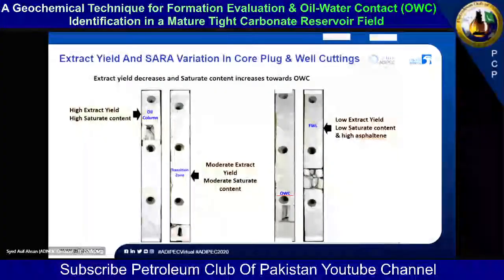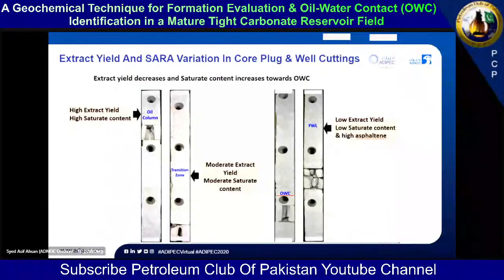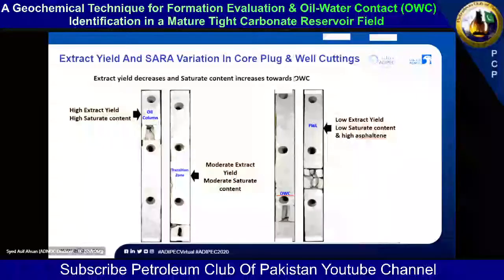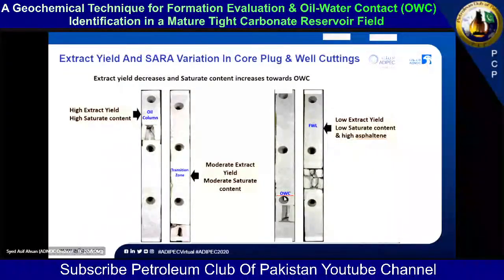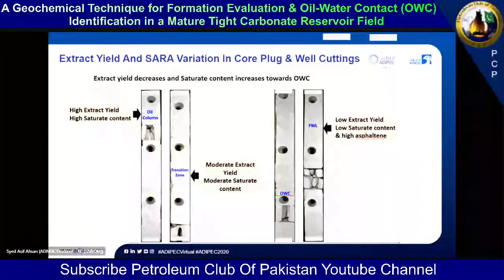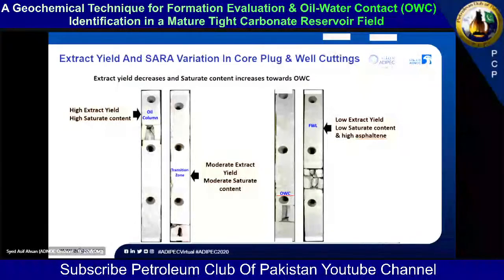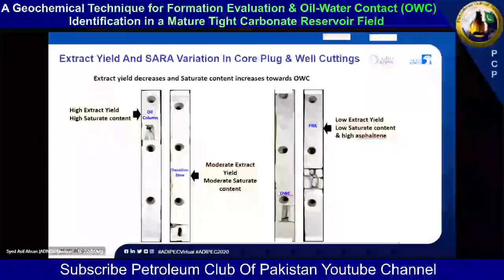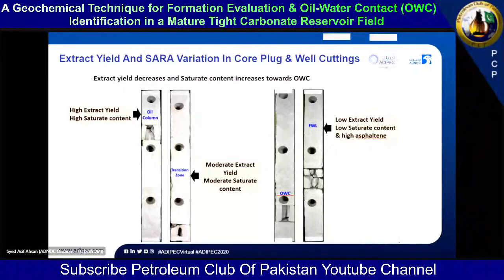So what happens, this is a real core from one of the wells that I showed you in the previous slide. Extract yield decreases and saturate content increases towards the oil-water contact. So as you move towards the oil-water contact, your extract yield is decreasing and saturate content is increasing. Up in the proper oil column, you will have several-fold higher extract yield values and higher saturate content. Okay, and within the transition zone, unfortunately, we do not have a defined oil-water column, because our reservoirs are tight and thin.